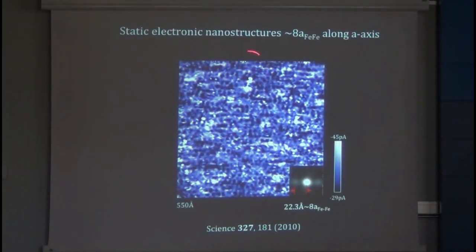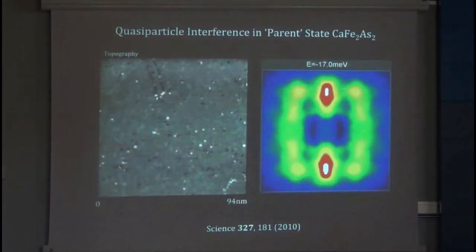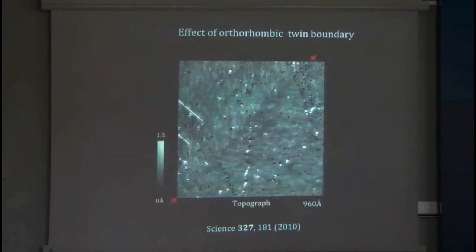We're also able to find that there's a lot of static electronic disorder, which we recently demonstrated is coming primarily from the dopant atoms. But it points in the opposite direction. It's rotated at 90 degrees to the direction of the delocalized states. I forgot to say, this dispersion here is certainly not consistent with a simple band structure theory for what we should observe. It tells us that something exotic and additional is happening.